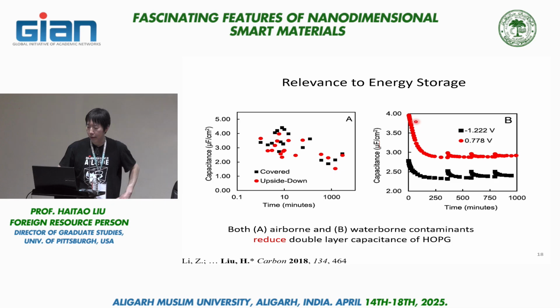Okay. We also did the same kind of measurement, but by continuously measuring the capacitance using EIS technique of the same electrode immersed in electrolyte solution. So what we find here is there's a rapid decline in the double layer capacitance within the first hour or two, and then it plateaus.